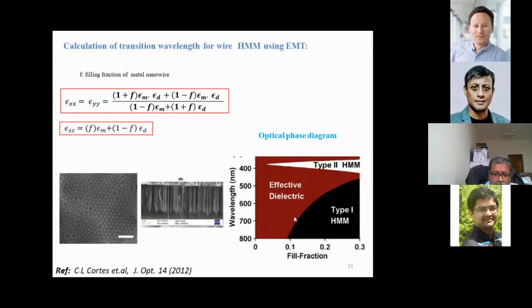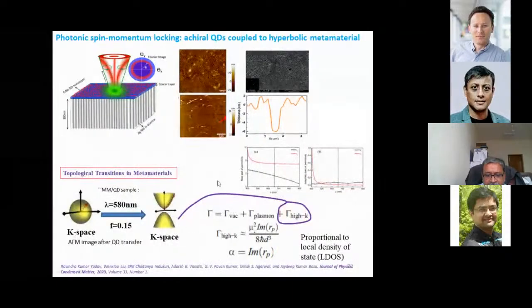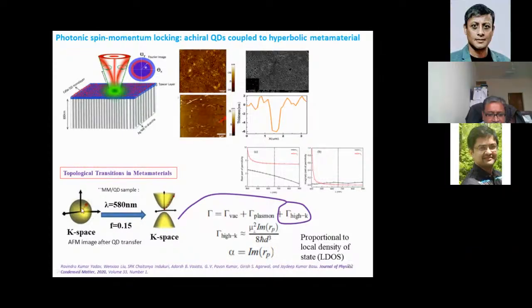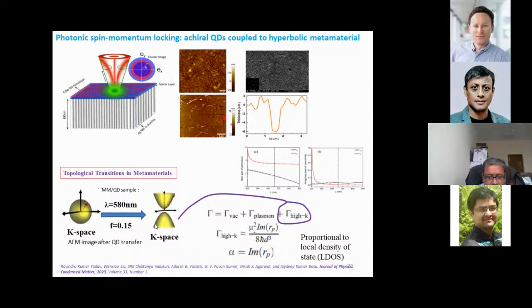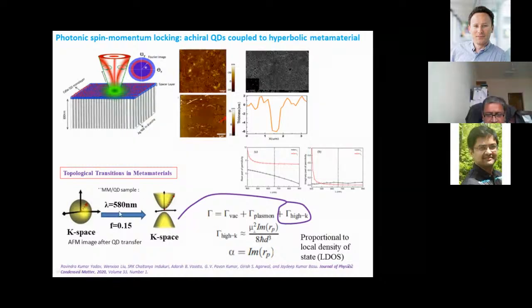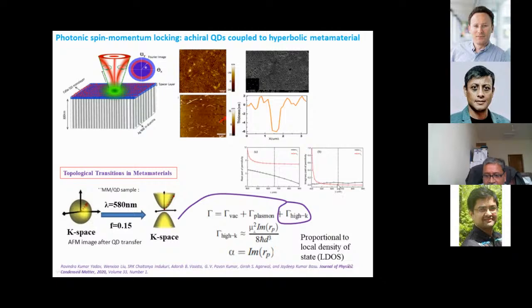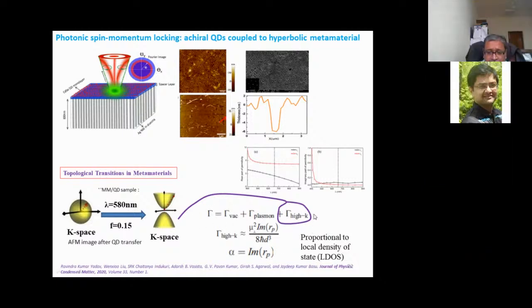And people have reported an optical topological transition when you go from an elliptic to a hyperbolic dispersion, and how that significantly changes the density of states. This is what is illustrated here: for a particular filling fraction, you can go from a dispersion like this, spherical or elliptical, to a hyperbolic one, as a function of wavelength. Here, for example, the permittivity as a function of wavelength can go through a change from positive to negative, and then you have this transition happening, and because of that you have the decay rate, which can be controlled by the availability of this high k.